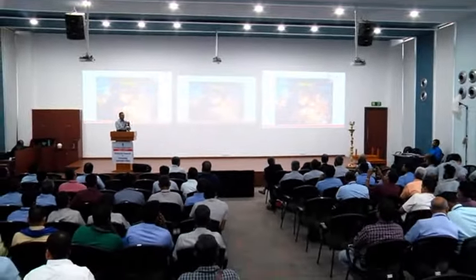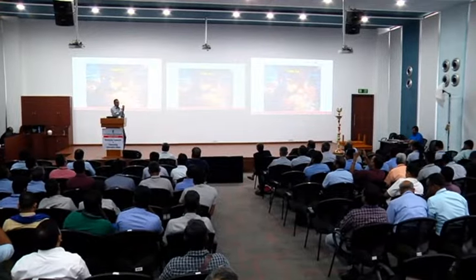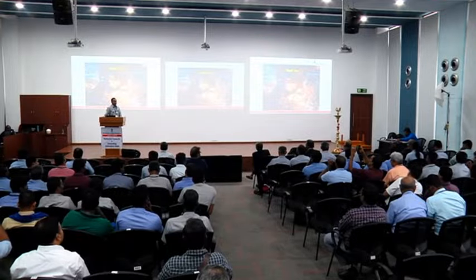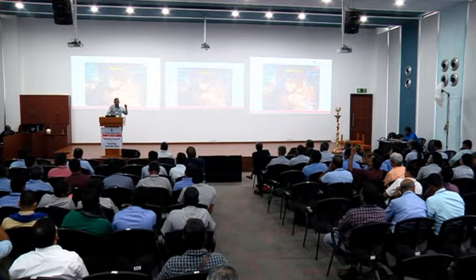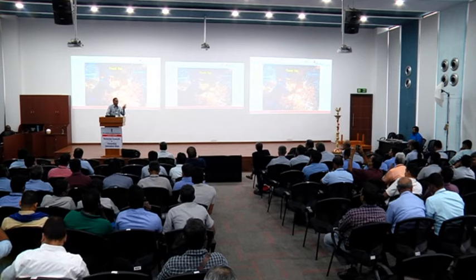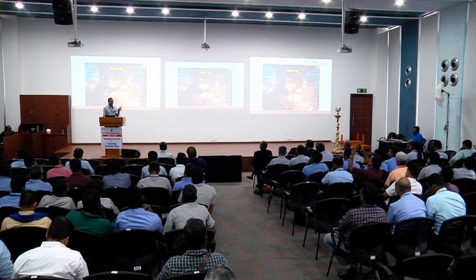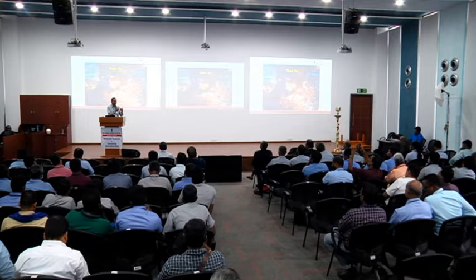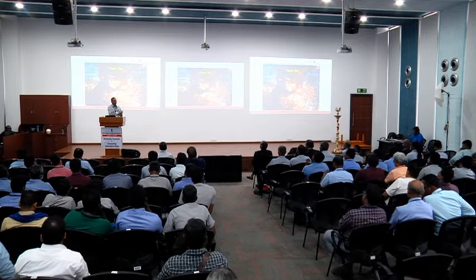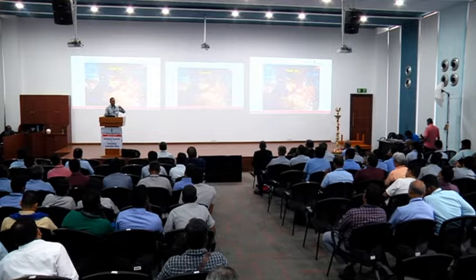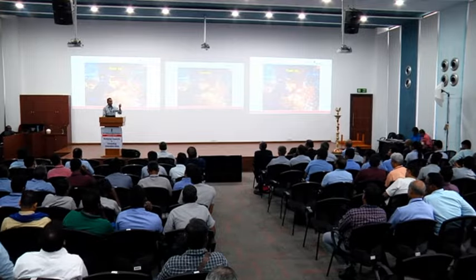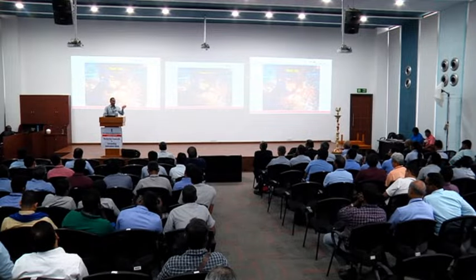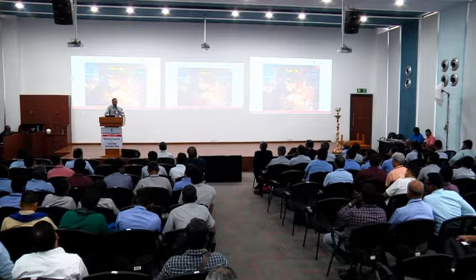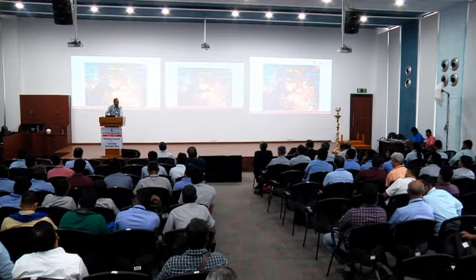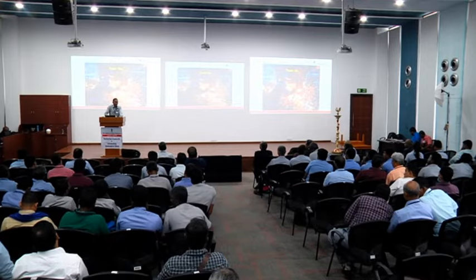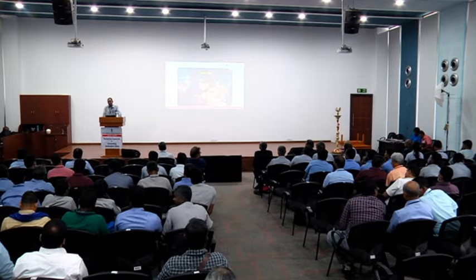See, pressurized, as I said, is where the choke is connected to the casting cavity. Pressurized is required for low wall thickness castings, and it is not suitable for green sand because the green sand mold is very soft. In a pressurized gating system, the green sand mold is likely to wash away because of the velocity of the metal, and then the sand particles will get stuck in the casting. So it depends on the wall thickness and the molding practice. We need to select either pressurized or non-pressurized. Normally, for cylinder blocks, pressurized gating is used. For other castings, non-pressurized. For green sand, non-pressurized.